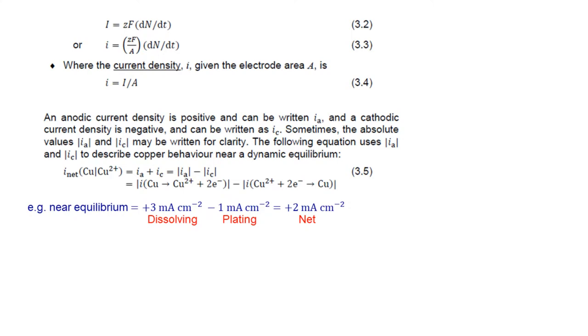So an example of this is shown in equation 3.5. This says we imagine we have a copper metal surface which is dissolving with some net rate described as the current density I subscript net for the copper electrode in electrode notation. But the environment in this case is only just causing active dissolution, active corrosion of the copper, and so this net dissolution is happening close to a dynamic equilibrium. That means the net metal dissolution rate is equal to the forwards anodic dissolution current density, labeled I subscript A, minus the value of the slower, but still happening, reverse cathodic process described I subscript C for its current density. The cathodic current density represents a small amount of electroplating happening simultaneously to a large amount of the metal dissolving.